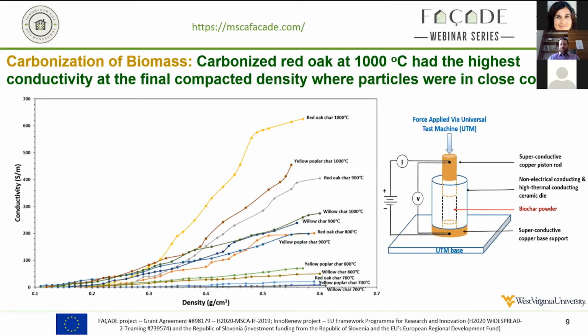Mainly the key takeaway here is, if you're looking at these yellow poplar, willow, and red oak biochar made at 700 degrees Celsius in the bottom, you don't really get much conductivity. It's not until you start getting to 800, 900, 1,000 degrees Celsius that you actually start seeing anything really good in terms of conductivity. So if you're producing biochar at 500 degrees Celsius, thinking you're going to be able to use that for conductive purposes, you won't be able to. But if your intention is to use this for soil amendments, we're wasting energy by going up to this 700 degrees. So it goes back to, what are you trying to use this material for? And that really changes how you're going to do the carbonization.